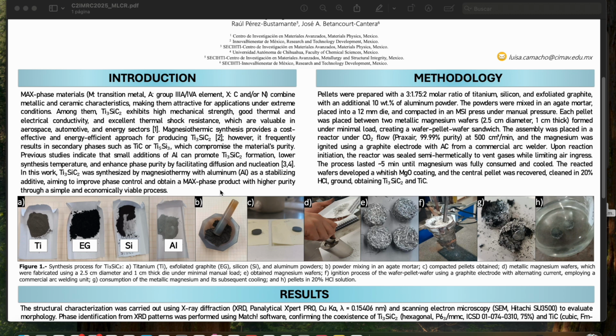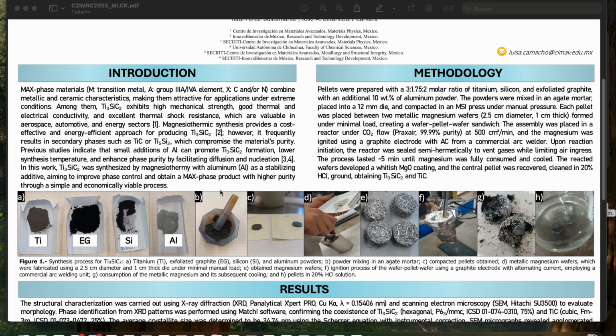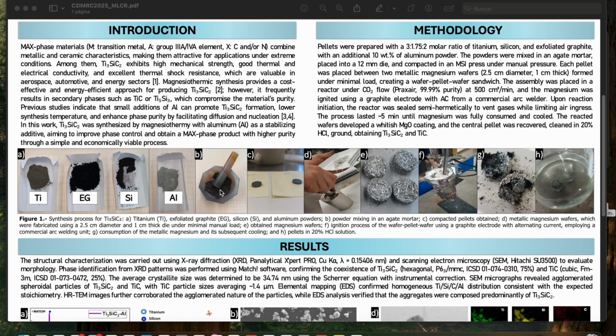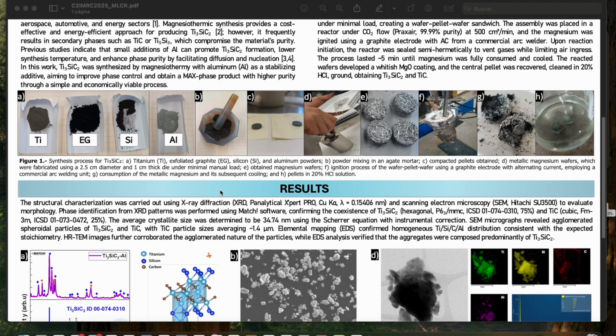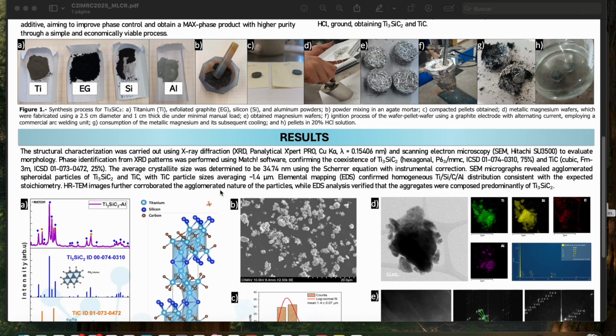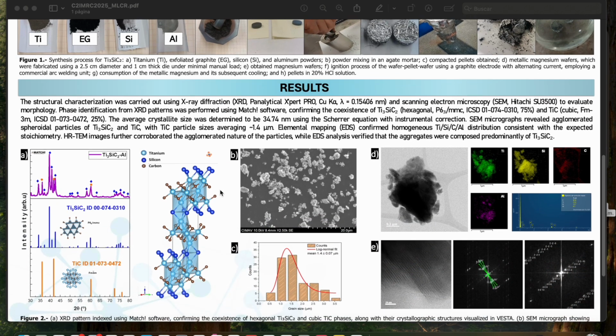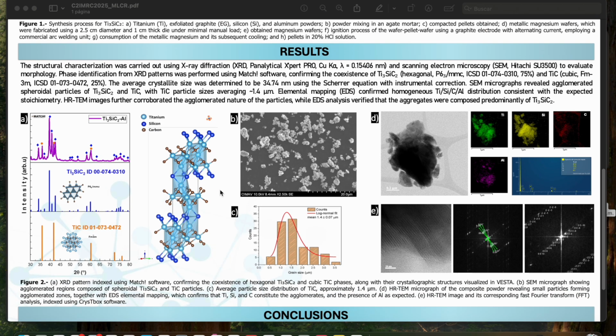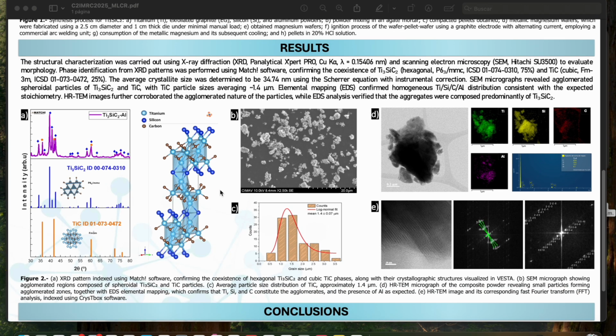Ignition used a graphite electrode with an AC arc welder, and the reaction was allowed to run to full Mg consumption before cooling. The post-treatment is intentionally minimal to keep barriers low. The reacted pellet was cleaned in 20% HCl to dissolve MgO and other soluble products, then ground for characterization. This workflow favors reproducibility, short cycle time, and compatibility with common lab hardware rather than specialized atmospheres or pressure vessels.